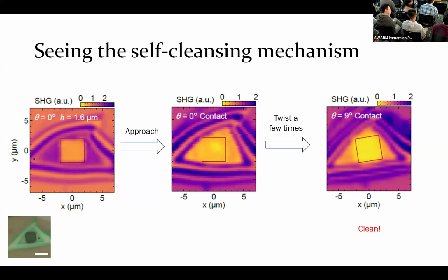How do you control the initial angle? That's a very good question. To repeat the question: how do we control the initial angle between the two materials? For hBN, we can determine its lattice orientation also by second harmonic generation. We first pre-screen the flakes that we exfoliated to know their lattice orientations, and then when we put them onto the MEMS or the substrate, we already know the orientation, so we can align them under the microscope so that initially they are close to 0 degrees. It's not exact, but within a few degrees is possible. And the rest we just use the MEMS to cover the range of twist.